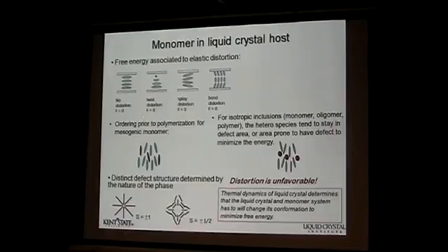And if you put in another heterogeneous species, that's going to cause some kind of disruption of the orientation of your host. But if you have some alignment like this, for example, rubbing direction in this direction, rubbing direction in that direction, say parallel to each other with respect to the rubbing direction. Okay, so they are now at 0 degree difference. And in that case, if you can create some small pre-tilt, for example, 2 degrees to 10 degrees, sometimes people even think about 45 degrees. So you get this splay-like structure. This is more like splay, actually, of the directors of the liquid crystal.